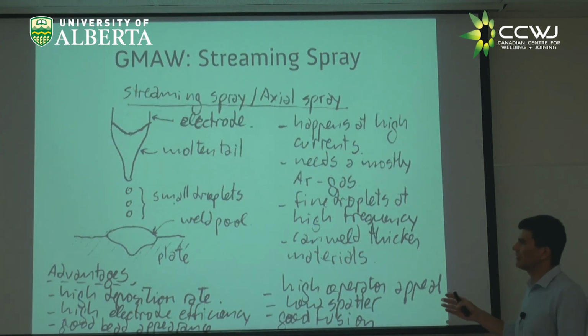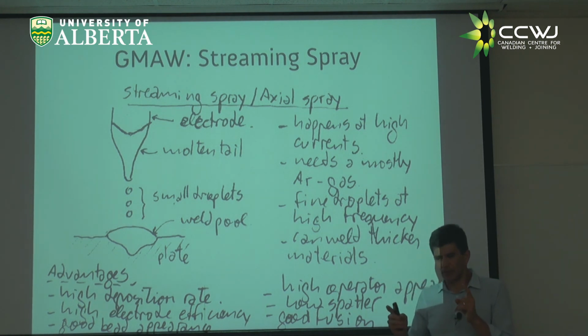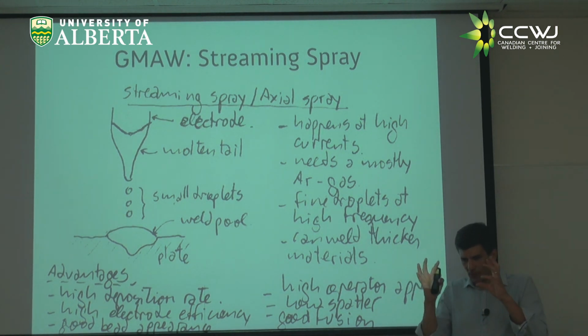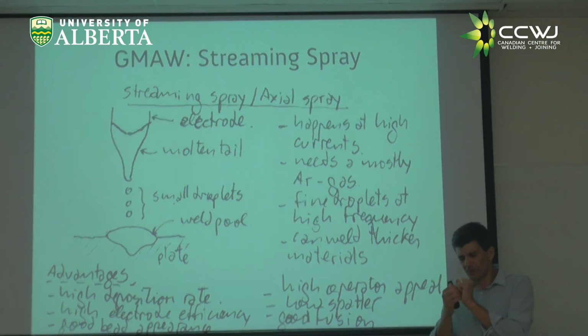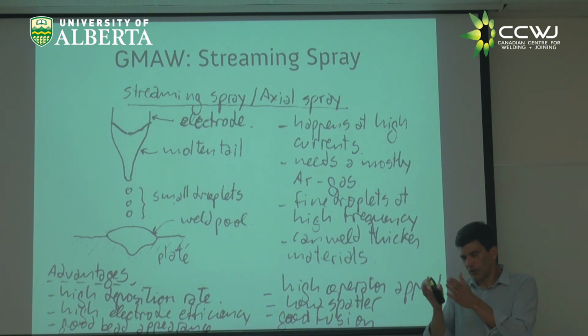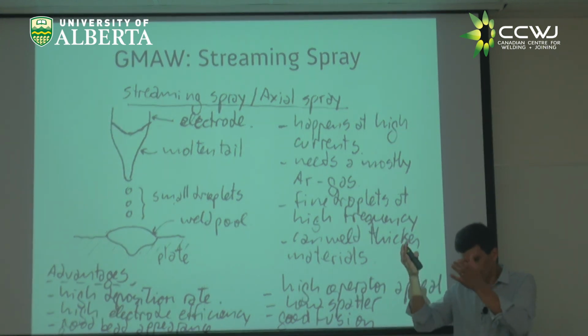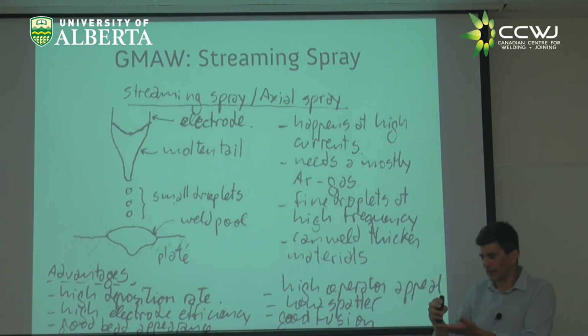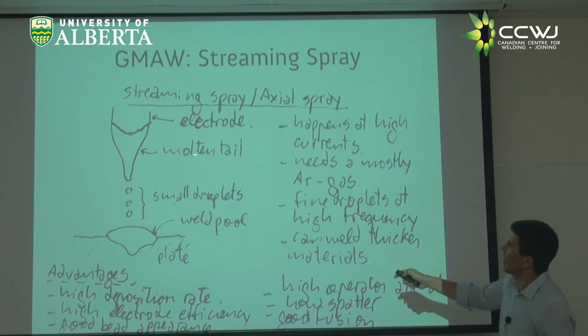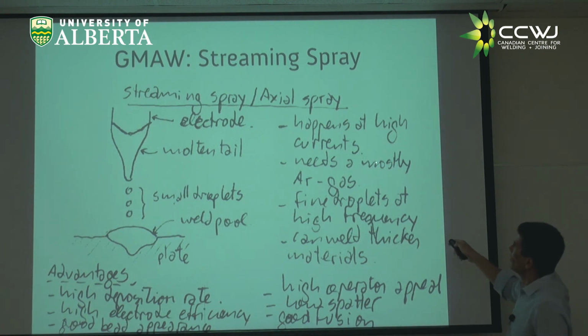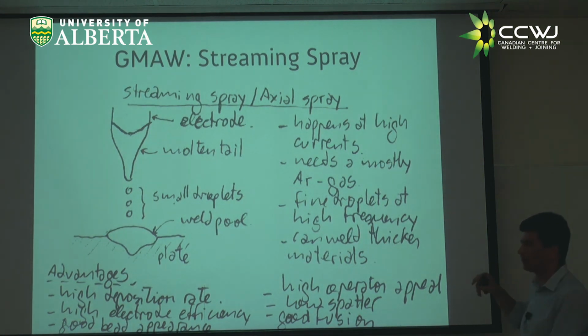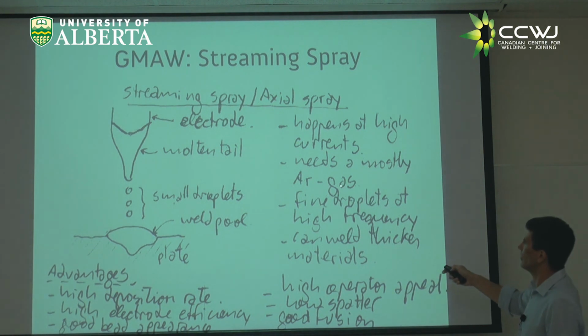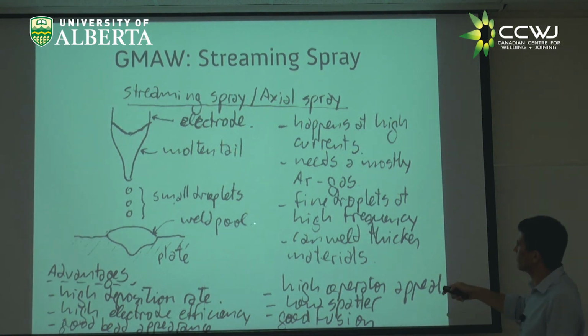Spray transfer, and I'm calling this streaming spray. You saw an intermediate thing called projected spray. So you have globular until the globular is so small that it's kind of a mini globular, right? That's called projected spray. At that point, the electromagnetic forces are pinching enough to eject the droplet, right? And then when the electromagnetic forces are huge, you just pinch a long tail, and that is called streaming spray. So streaming spray happens at high currents. You need mostly argon gas, I would say less than 20% CO2. You have small droplets at high frequency.